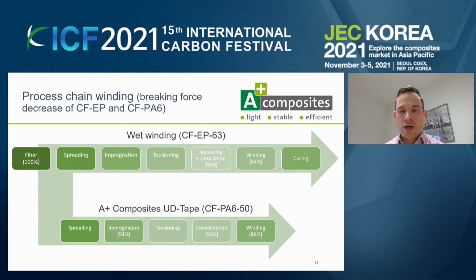If you now wind it up on a circular surface, depending on the diameter, you will even have higher losses. And if you have a mindset that we only investigated a single tow, if you now wind it up with several layers, this decrease will be even higher. This effect is well reported in literature. There are many papers available which give answers why this is, but one big point is the squeezing out and the irregular surface of the wet winding process.